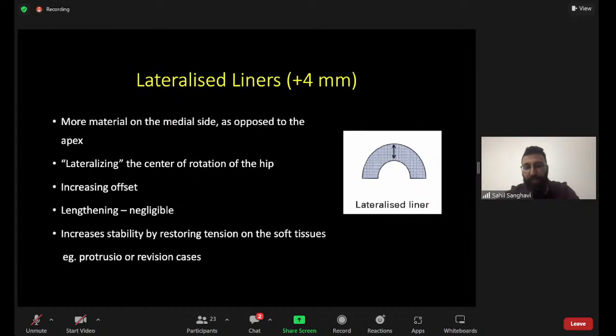Then you have lateralized liners or the +4 millimeter liners, wherein there is more material on the medial side. So as you can see in the image here, the medial side of the liner is thicker as compared to the edges. And this allows you some lateralization of the center of rotation of the hip by increasing the offset. It also causes some lengthening, but that is negligible. And the main advantage of this lateralized polyethylene liner is it increases the stability by restoring tension on the soft tissues, which can be useful for revision cases or cases of protrusion.